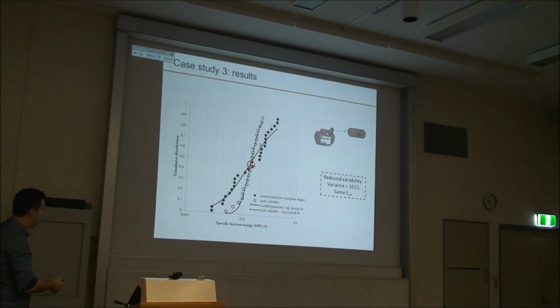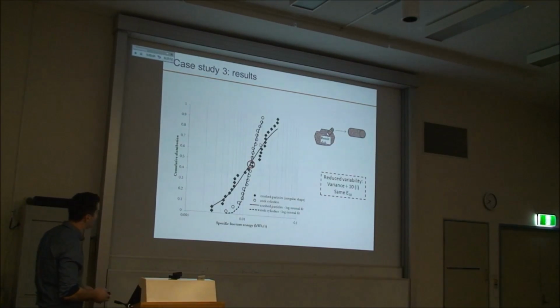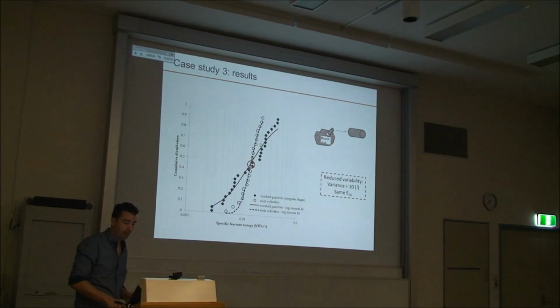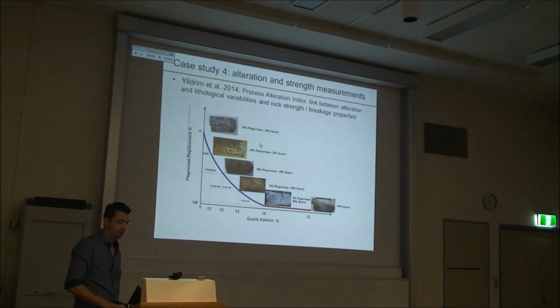And the empty symbols, the circles here, show the results with the cylindrical particles. So indeed, the variance of the distribution was divided by 10. So we managed to get the same fracture energy, but with a much steeper distribution. So this was quite interesting, and I'm going to show you an application of this in a minute.